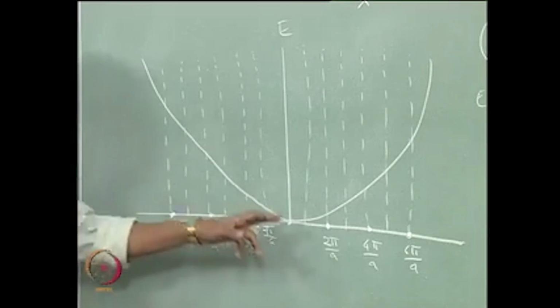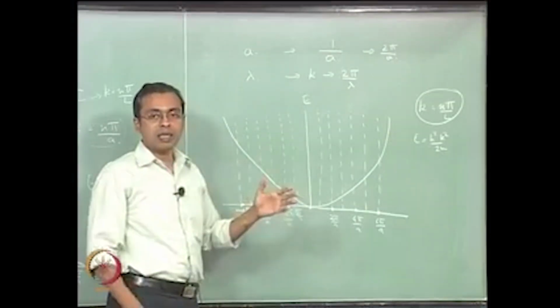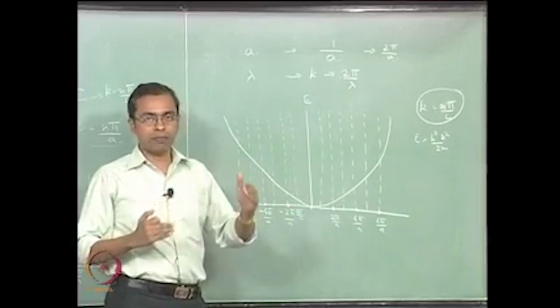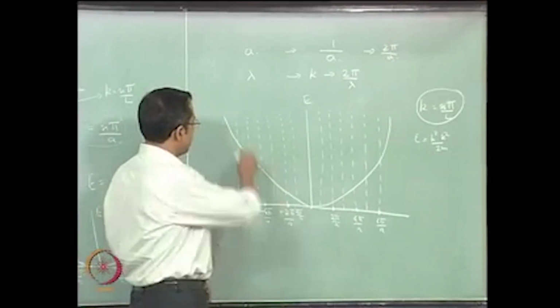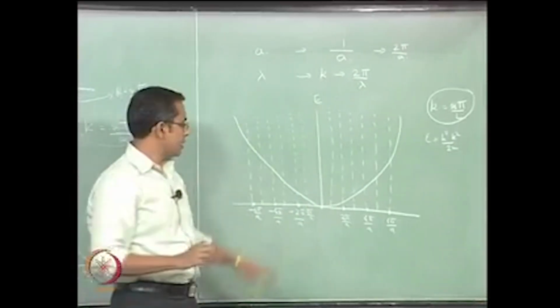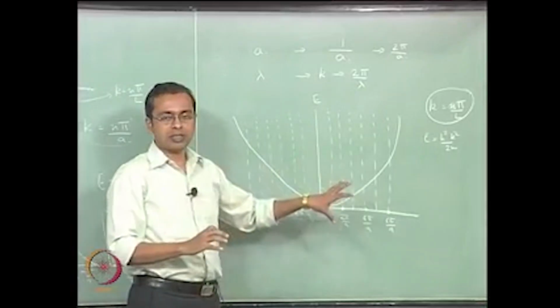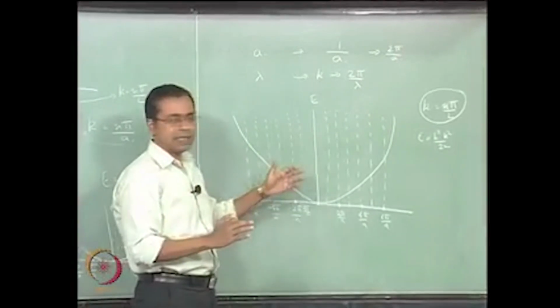So at all of these locations diffraction is occurring, and wherever diffraction occurs, it turns out that certain levels of energy become forbidden, alright. So at Brillouin zone boundaries this E versus k relationship begins to distort, okay, and it is a result of this distortion that results in the band structure of the material, okay. Right now I am saying that in a general sense.